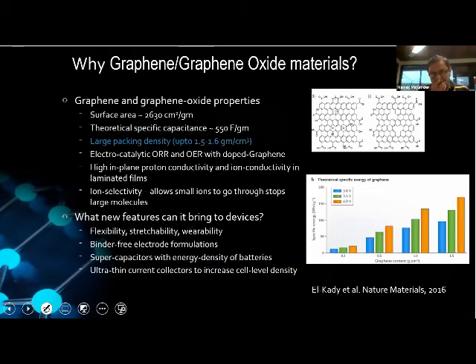One of the questions we have to ask is why graphene or graphene oxide materials? Now, Baohua pointed out that there are many advantages in using graphene that include high conductivity, good thermal properties. But for energy storage applications, one of the key things is surface area, which she also pointed out. Now, it turns out that graphene has a theoretical specific capacitance of about 550 farads per gram, which is essentially unheard of in the literature of supercapacitor materials.